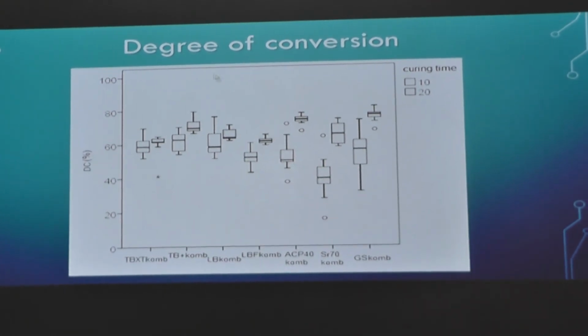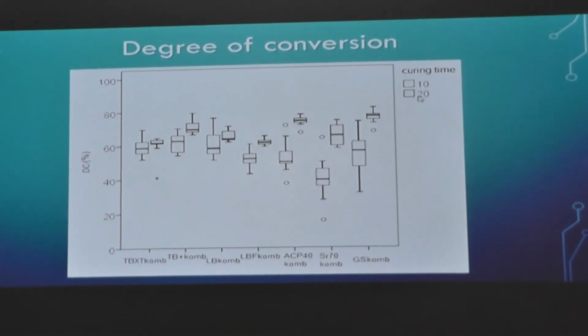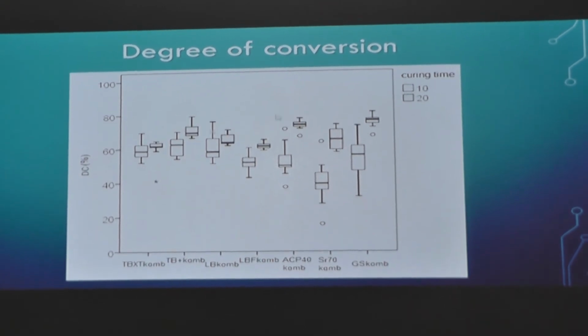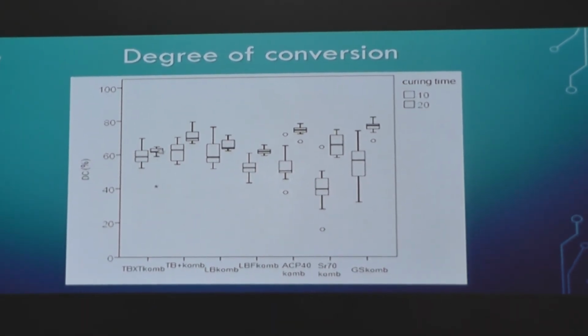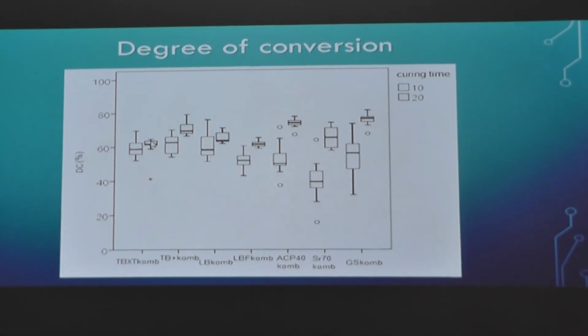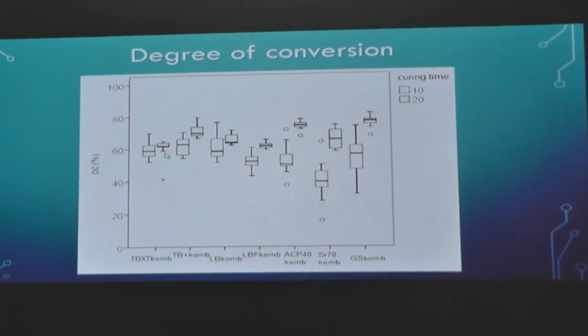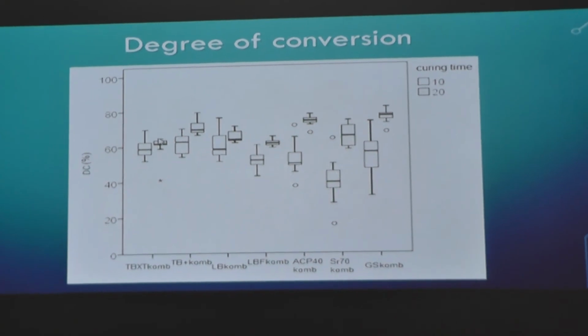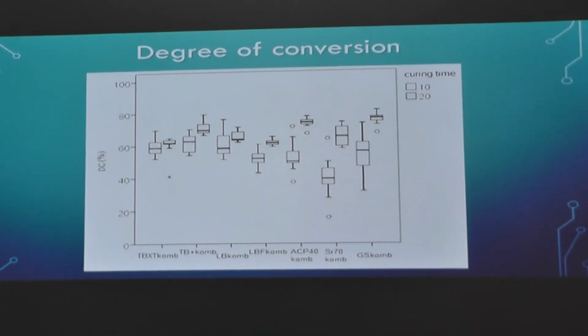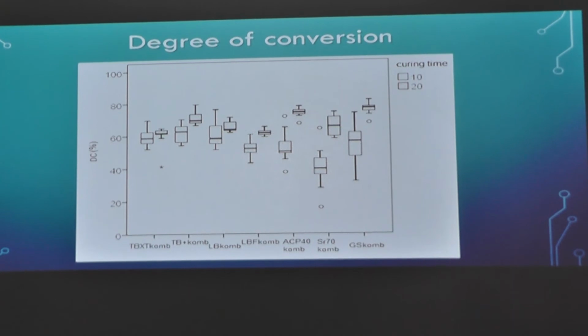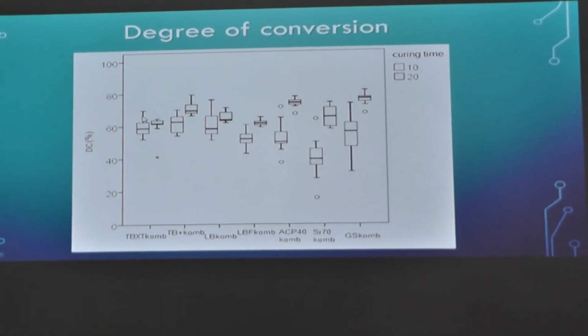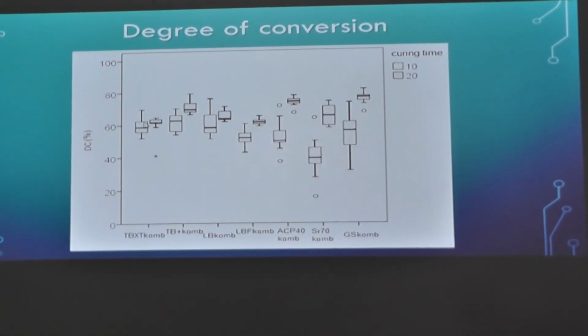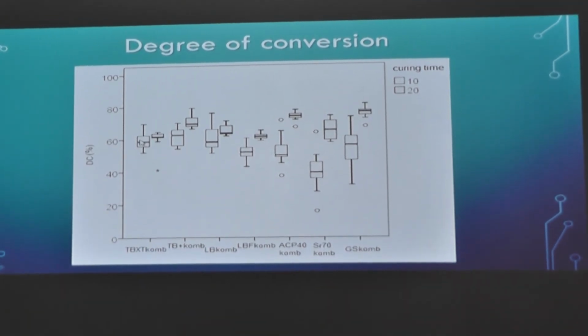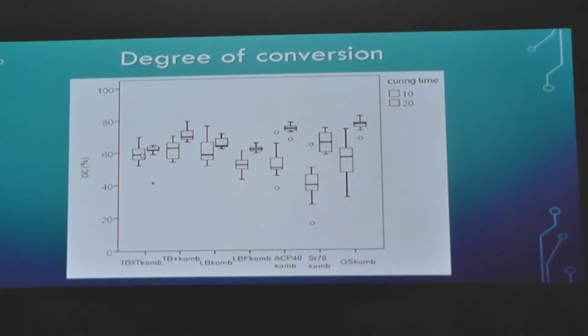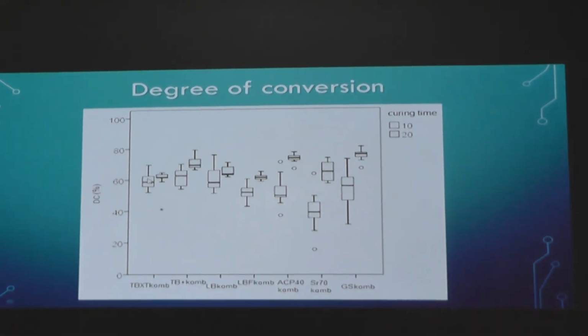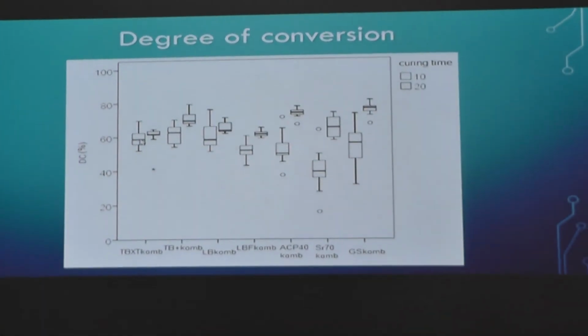And one last thing that I wanted to show you, so the color is not seen, but this curing time, this is if it's cured for 10 seconds and this is if it is cured for 20 seconds. It is the degree of conversion, so how many of the double bonds in the material actually converted into single bonds. And for Transbond, so this is something that you can take home perhaps, the difference is not significant. The conversion rate is the same if you cure it for 10 or 20 seconds.